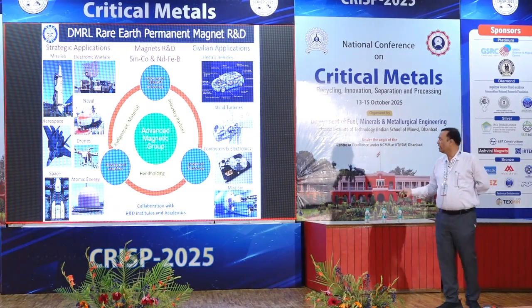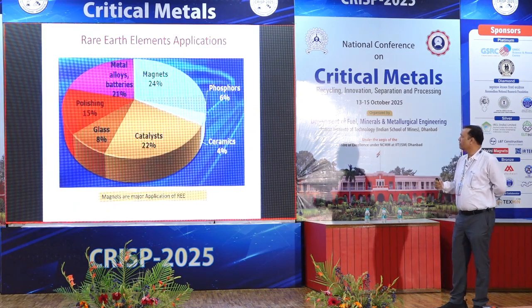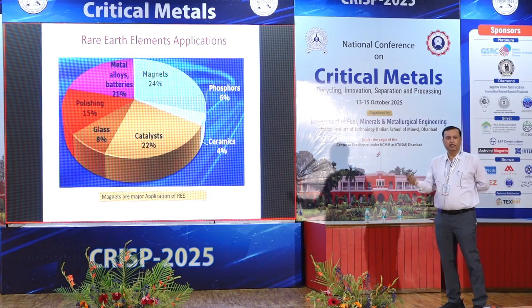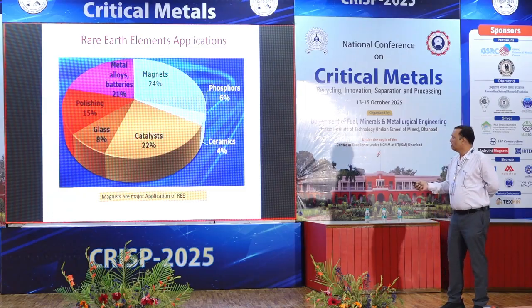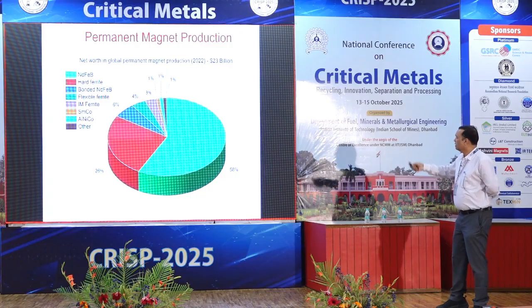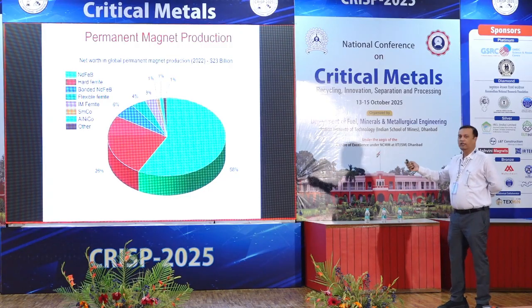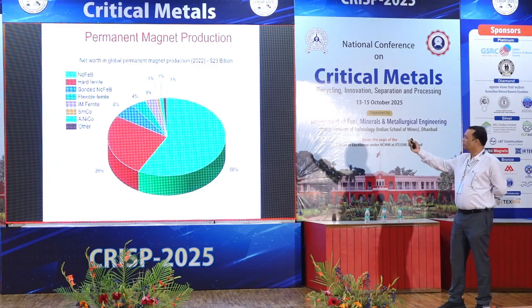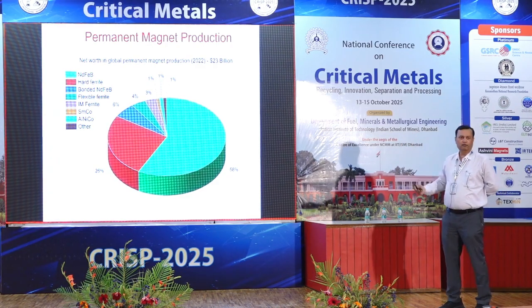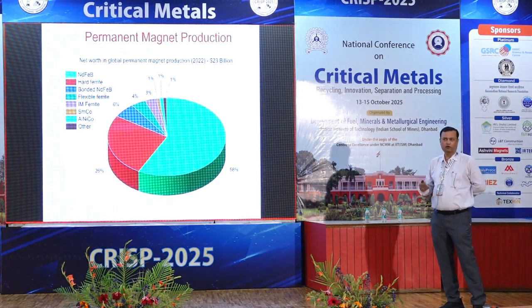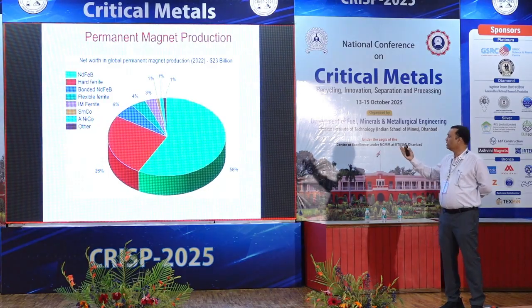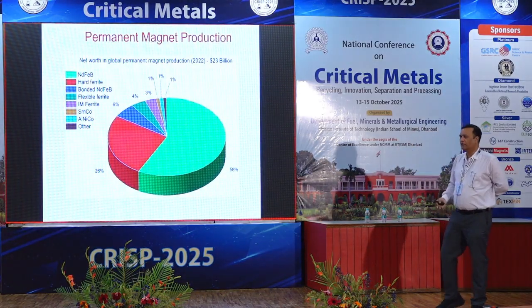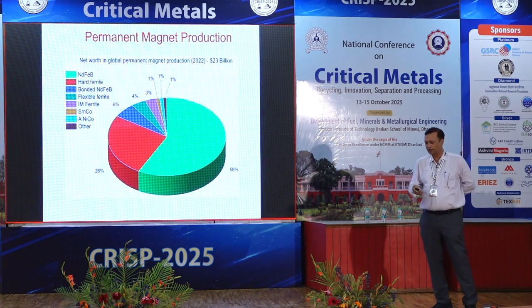If you look at the use of rare earth elements, 24% is used for making magnets, either NdFeB or samarium cobalt. If you consider all permanent magnets, 58% is NdFeB magnet. And samarium cobalt is only around 1 weight percent. If you look at the worldwide production by volume or weight, it is only 1 weight percent. The reason being that samarium cobalt is used only for strategic applications.